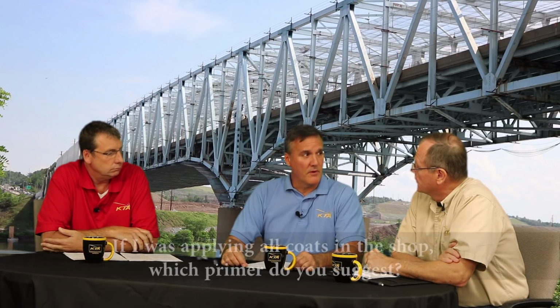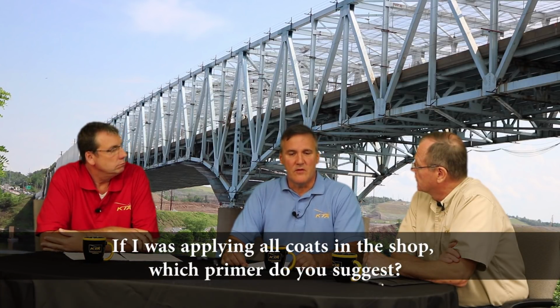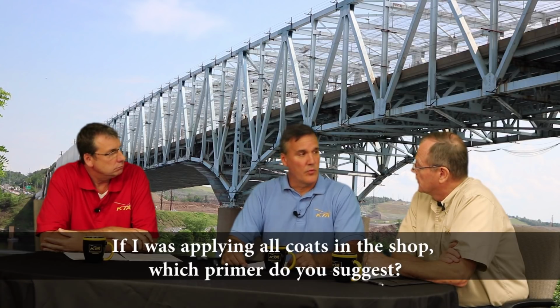Organic zinc in the shop is becoming very popular right now, primarily due to the fact that when we have the inorganic zincs applied in the shop, we have to constantly monitor the relative humidities because the ethyl silicate binders used in the inorganic zinc primers react with moisture to cure. If we have insufficient moisture, we have prolonged cure times. With the organic zincs, because the epoxy zinc-rich coatings are chemically cured, they have a tendency to react faster because they're more temperature dependent. The heat that we use in the shop sometimes isn't there. We don't have the heating characteristics, but they do have accelerators and faster curing organic zincs nowadays. And because they have accelerators and faster recoat windows, they become more popular in the shop. For production reasons, it sounds like. For production reasons. Recoat it rather quickly and get the